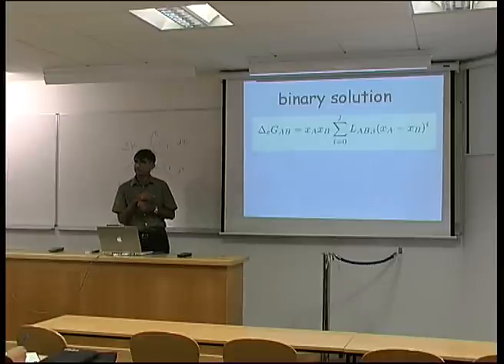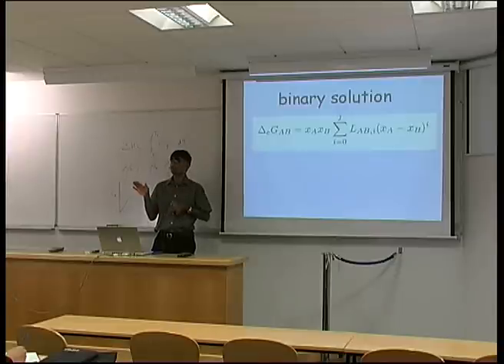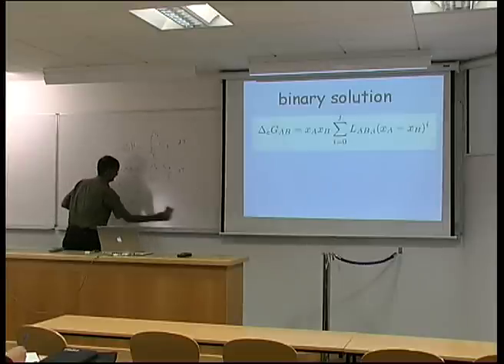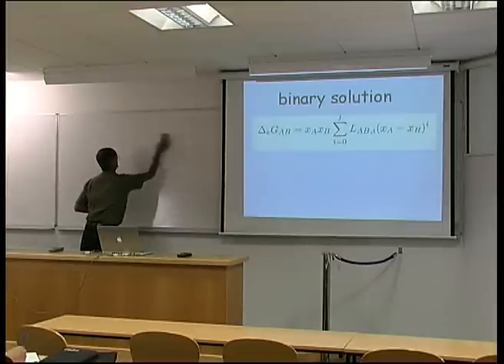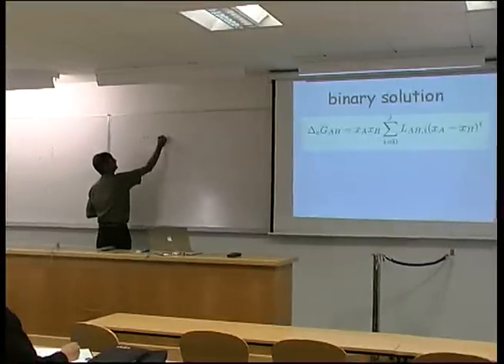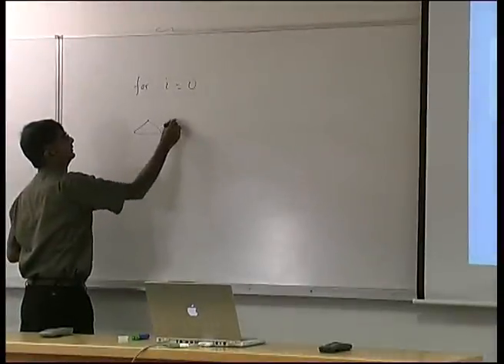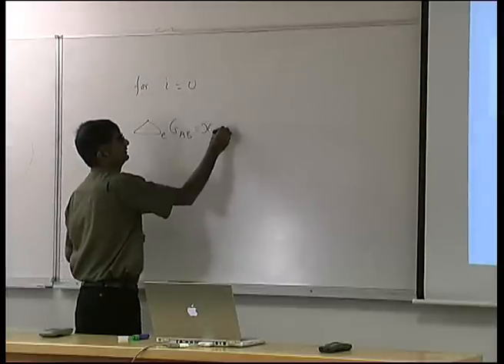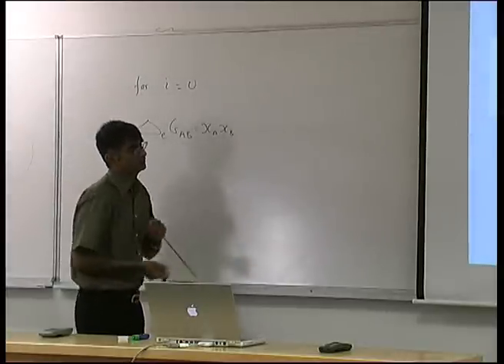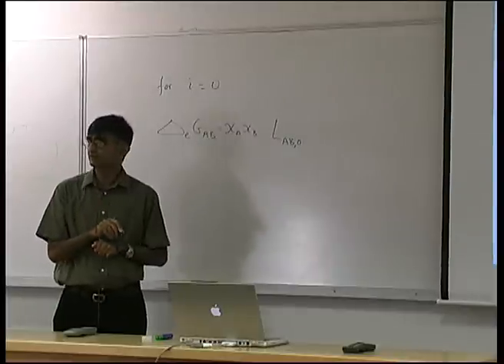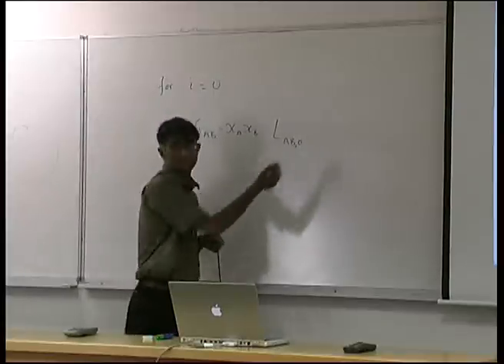This is the concentration of A, the concentration of B. This is a coefficient and this is an exponent and this is XA minus XB. And we can use as many terms here as we like to accurately represent the experimental data. Now, supposing that I equals 0, we only use the first term in this equation. What will this reduce to? So for I equals 0, well XA and XB are still there, XA, XB and we are only going to use one term, I equals 0. So we will have this coefficient LAB0. What about the bracket? It goes to one. It goes to one, doesn't it? Now, does this ring a bell?